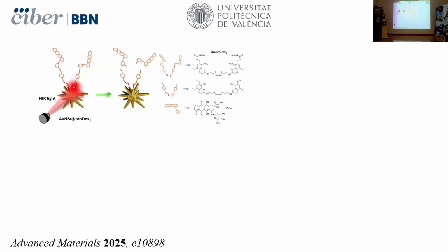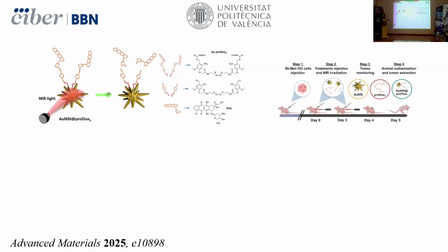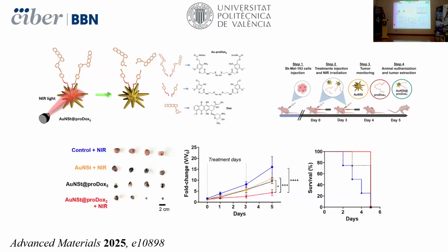So the idea is that irradiation causes the accumulation of the electromagnetic field, which breaks that bond here and releases the doxorubicin free. It's like a kind of prodrug. So the system works, and we have tested that even in in vivo models. We grow the tumor, we inject the nanostars, that system, in the tumor, we irradiate and are able to deliver the doxorubicin. This is just a proof of concept with quite good results in terms of reduction of the tumor size compared with other controls. So this is not hyperthermia, it's just the release of doxorubicin using light.